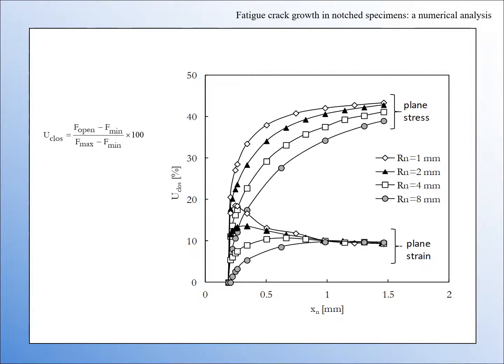This figure shows the values of crack closure, which are higher for plane stress state and decrease with the increase of notch radius.